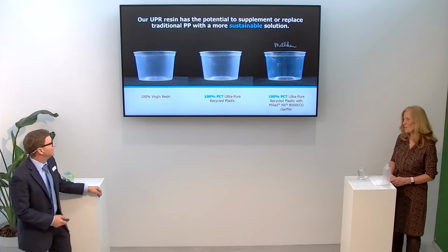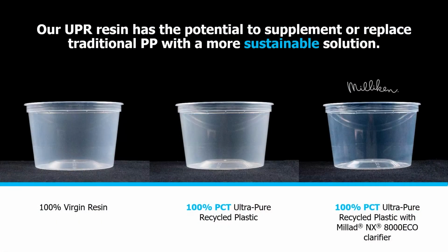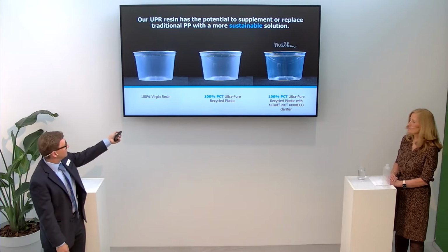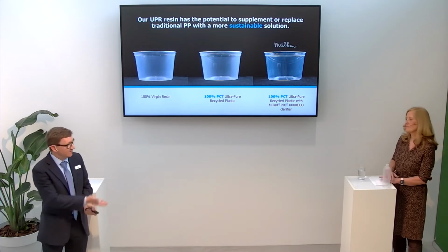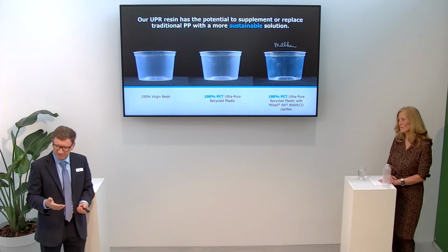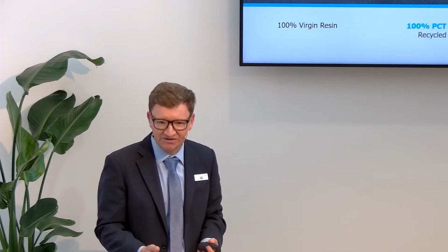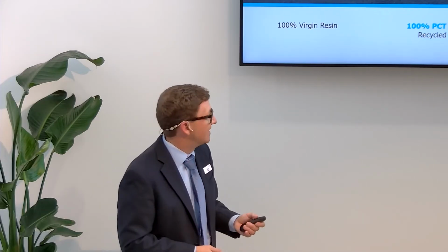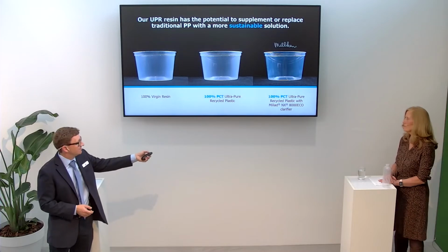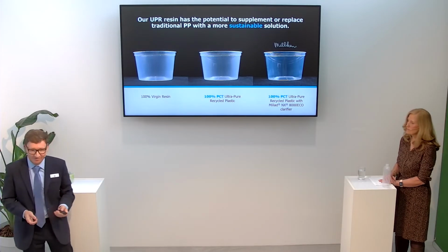Yeah, thanks, Tamsin. You're welcome. So one thing I'll point out is if you look at just their base material and compare that to a homopolymer, they actually get quite a bit better clarity. And a lot of that is due to the dissolution process and the removal of the oligomers and low molecular weight fraction that can cloud, and also some of the additives in there. And then obviously with NX8000 Eco, we're able to improve that clarity a bit.